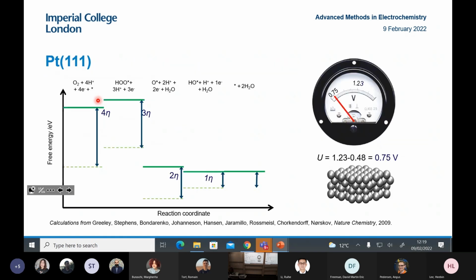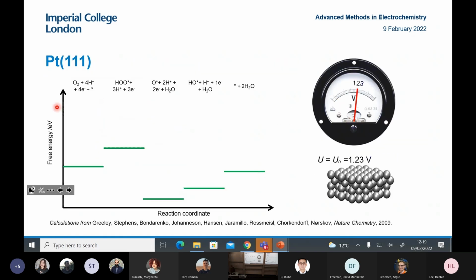So you can imagine you could ideally find a better catalyst if you could independently tune the binding energies of the different intermediates. So maybe you could stabilize the OOH intermediate and destabilize oxygen and OH. However, it turns out it's not possible to do that. As I already mentioned, they all bind via the oxygen atom. When they all bind by the oxygen atom, it means you can't tune each one independently of each other.